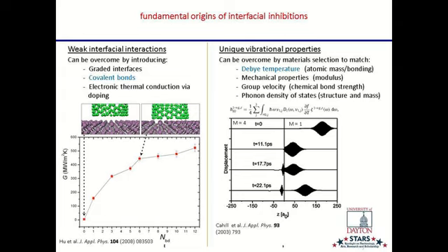And as that wave comes to that interface, only a tiny fraction of the energy propagates through the interface. A lot of it is reflected back. So this big glob of energy is just coming back. It's trapped in this material, just like the heat was trapped in this carbon nanotube. So we've got to try and overcome these interfacial effects to really realize the utility of these carbon nanotubes. Even a fraction of their utility would be amazing. It would really change the way that we could make materials or make components involving these materials.